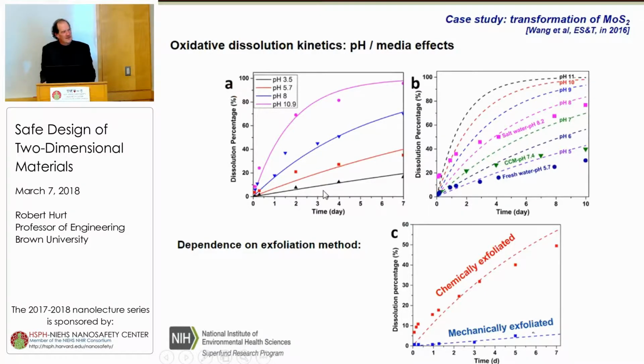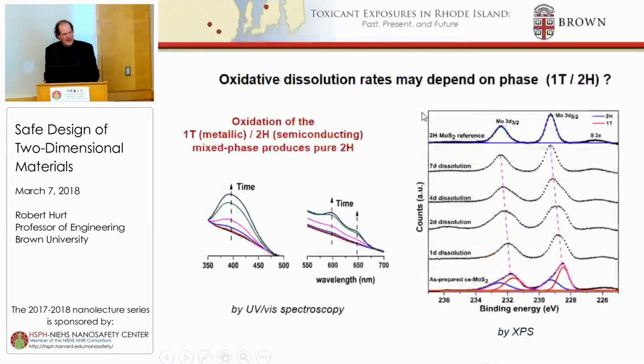Now, the dissolution rate turns out to be pH dependent. It's faster at high pH, which is the inverse of some systems. But what's really neat is that the chemically exfoliated material oxidizes and dissolves much faster than the mechanically exfoliated material. Why is that? Well, one idea would be that it really depends on phase, that the metal oxidizes faster than the semiconductor. And this is XPS data.